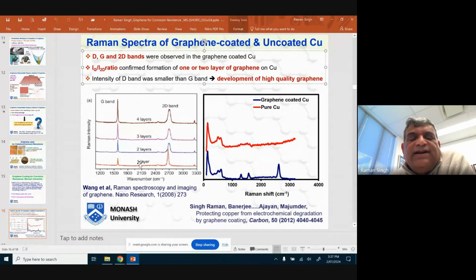Because as I increase the number of layers of graphene on top of metal, the G peak starts to become taller and taller compared to the 2D peak. As you can see, for two and more layers, the G peak is taller compared to the 2D peak. So what we got was single layer graphene, because the G peak is dwarfed, shorter compared to the 2D peak.